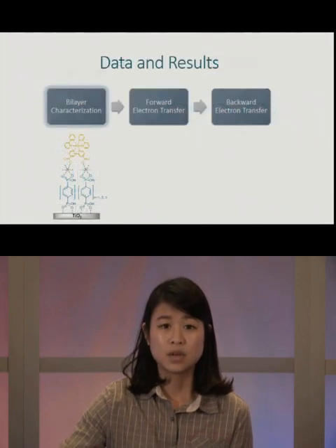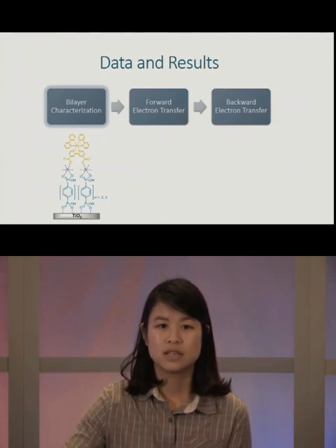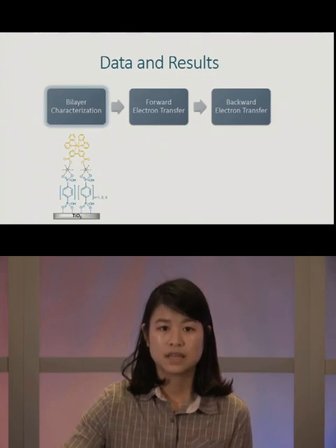And we characterize these bilayers through ATR-IR and UV-Vis. When we couple them together, we have very strong evidence to suggest that the phosphonate group and the zirconia are binding together, and it supports the bilayer structure.